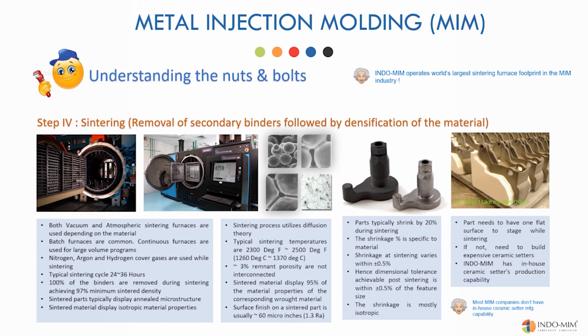As you see, there is a significant size difference between a green part and a sintered part. The component shown is made of stainless steel 17-4pH, which has 16% shrinkage. Shrinkage percentage at the sintering stage varies by 1% total. This variation determines the dimensional tolerance achievable after sintering. Most of the MIM companies achieve dimensional tolerance on the components within plus or minus 0.5% of the feature size. With better process control and equipment, it is possible to achieve plus or minus 0.25% of the feature size.